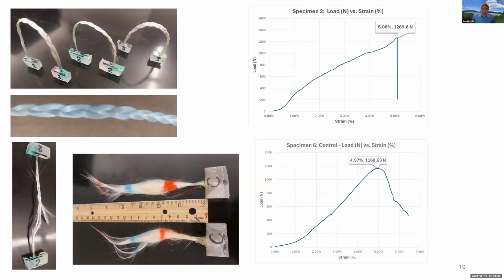Very good. So again, by this morning, we have a preliminary test result. Here you can see these are braided bundles, and then we have the epoxy at the clamps so that we were able to clamp them into the MTS machine to do some tensile testing. Here is a close look at the braided fiber, and here it is after the tensile testing. This figure shows the straight fibers after the tensile fracture. Both samples are made with the same 3 rovings of glass fibers.